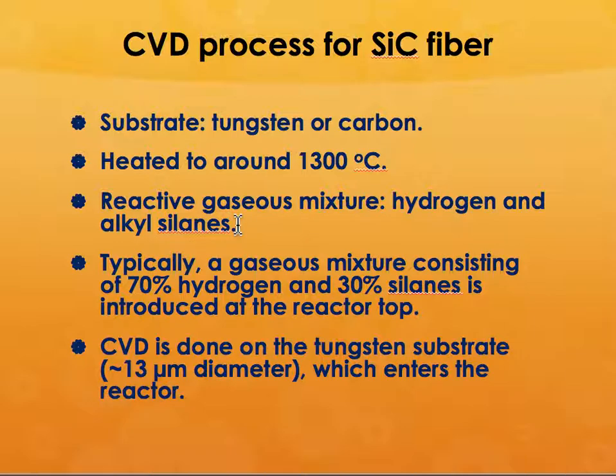So the silicon carbide matrix was deposited around a wire of tungsten or carbon heated to around 1300 degrees centigrade. You take a reactive gaseous mixture such as hydrogen and methyl trichlorosilane, or what you would euphemistically call alkyl silanes. Don't worry too much about the chemical structure or chemical nature of the gas itself. But just know that you are taking a highly reactive material such as methyl trichlorosilane, which is a dangerous gas, and you are blending it with hydrogen and reacting it at around 1300 degrees centigrade.